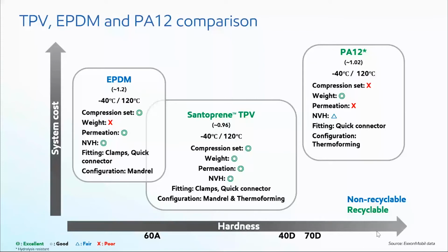Whereas EPDM plays in the softer hardness range like 60 Shore A, and PA12 hoses are very hard, 70 Shore D and above. Also, there are a lot of other factors like the density. The density of Santoprene is very low. It is about 0.96, whereas an EPDM compound is very, very heavy. The density is 1.2, and it adds to the weight of the part made out of EPDM.